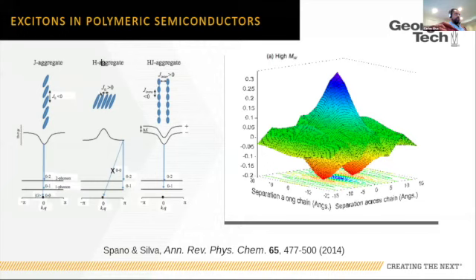This is an H aggregate, and in polymers where we have chains that may align in a cofacial way, we can have an intrachain exciton dispersion, but we can also have an interchain exciton dispersion, and that is what we call the hybrid HJ aggregate. That is really the situation, and the interplay between these forces really determines what the exciton coherence length is along the chain as well as between chains, and this is what we describe in this two-dimensional coherence function here.